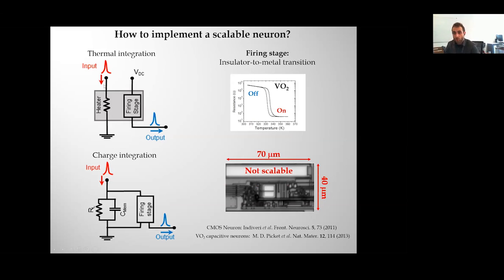In our case, we would have a resistor that would act as a heater, and that would be the integrator. You send current pulses to this heater, and each current pulse is going to elevate the temperature a little bit more. Then you have a firing stage, which is very sensitive to changes in temperature, which is electrically disconnected, but is thermally coupled to this heater. So there is very good thermal transfer between both of them. When this is excited above some temperature threshold, it outputs a spike. And for this temperature-sensitive firing stage, we decided to use VO2 because it has a really sharp dependence on temperature.